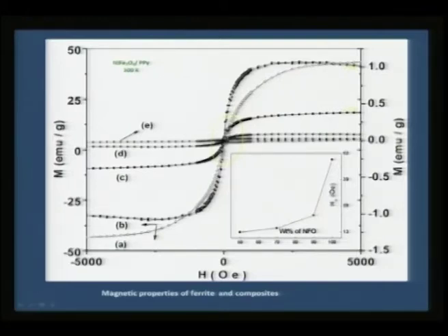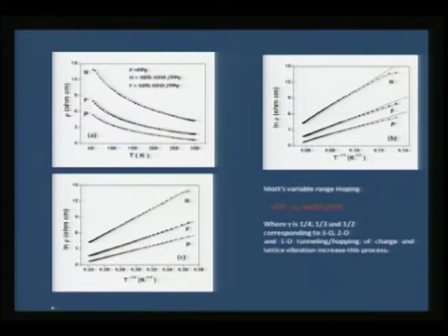And if one would plot the loading concentration of nickel ferrite as a function of the coercivity, one can say that there is a plateau between 50 to 90%. The coercivity does not seem to be largely affected by the coating, although there is a very small variation from 13 to 20 Oersted. So, the coercivity does not seem to be varying much, although the magnetic moment is sufficiently different in the polypyrrole coated nickel ferrite powders. And you can also make a plot of the resistivity versus temperature, showing that they all are magnetic and they are ferromagnetic as well as they are conducting. Only at low temperature you see this upturn in resistance, mainly that is coming because of the conduction mechanism.